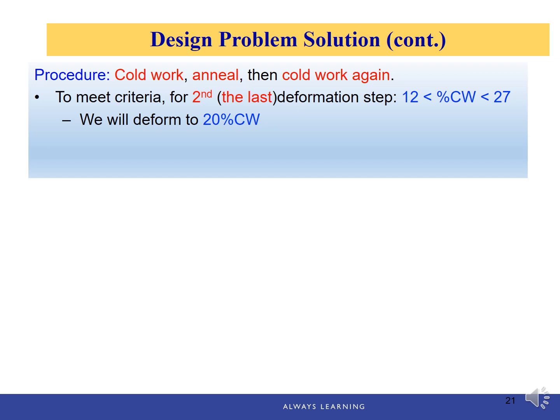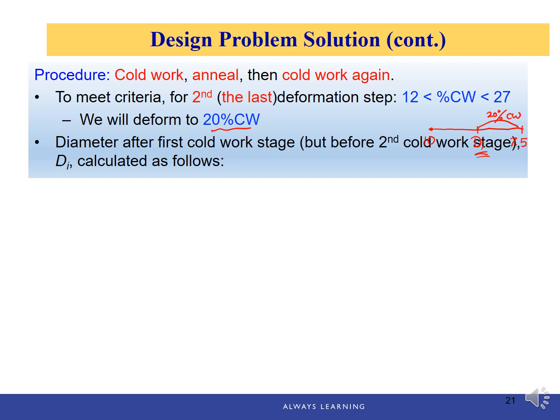Okay, now again, remember our plan includes an intermediate diameter. The initial one is 10, and there is an intermediate diameter, and the final diameter is 7.5. So in order to determine the percentage of cold work during the second stage of cold work, which is 20%, with this information we can find the intermediate diameter, and then we can check our final answers, or plan our procedure in more detail. Okay, so let's calculate the diameter after the first cold work stage, or the intermediate diameter D_I.